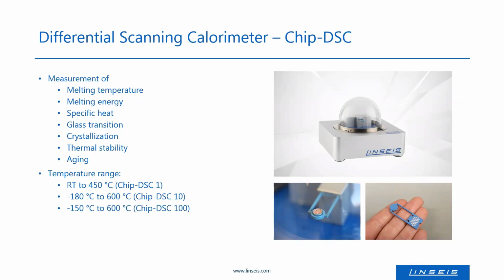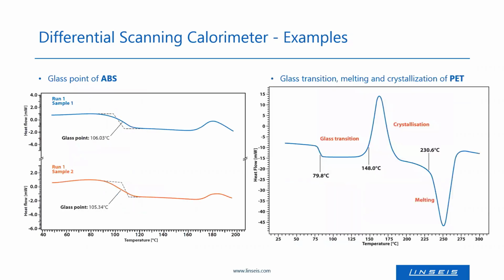So by that, one can really investigate the material in detail. Here are some examples for measurements performed by the calorimeter. On the left, you see the glass point of ABS. Here a temperature-dependent measurement was performed from slightly above 40 degrees Celsius to 200.